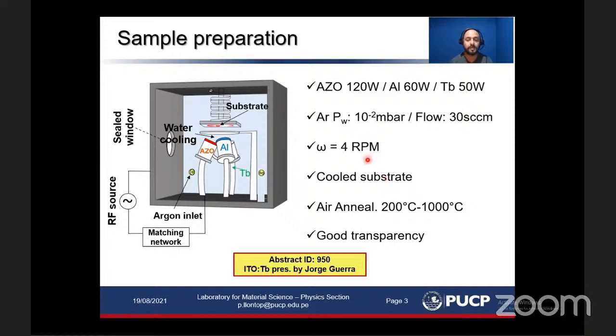With rare earth doped wide bandgap semiconductors, we cool down the sample to induce a rearrangement of the terbium ion in this case and its surroundings, to activate them by means of thermal annealing treatments. These thermal treatments were done in air atmosphere and in this temperature range. Both the as deposited and annealed samples showed good transparency. A similar approach was taken also for samples of terbium doped ITO. You can see the results in another presentation also in this conference.